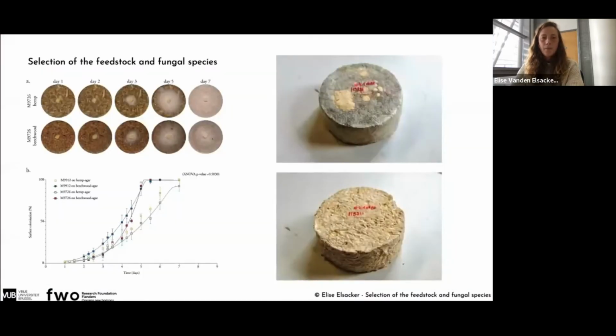Different types of fibers were also tested, and different species. Here we see the growth on hemp fibers and on beechwood fibers, where the beechwood fibers would be colonized a little bit faster than the hemp fibers. And different species, so this is Ganoderma lucidum, and this is Trametes versicolor. You clearly see a difference in growth behavior. So in the end, I decided to work with Ganoderma lucidum.